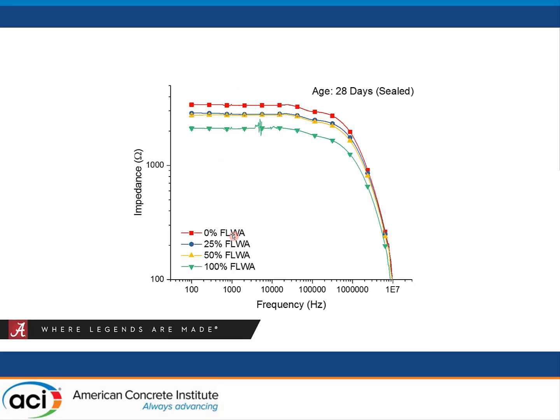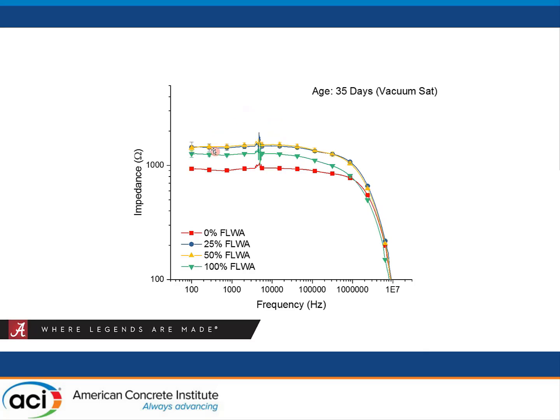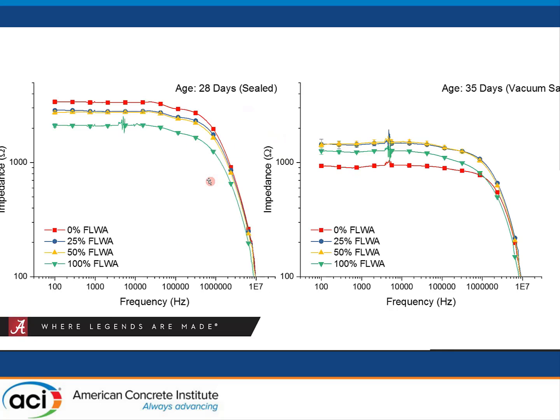Again, resistivity increases, and we have our non-internally cured mix with the highest impedance, what you could call moderately internally cured mixtures here, and then 100% lightweight down here. And then we vacuum saturate it. We oven dry and then vacuum saturate, and we see something very interesting happen. And we look at 28 days sealed, and then we oven dry and then vacuum saturate.